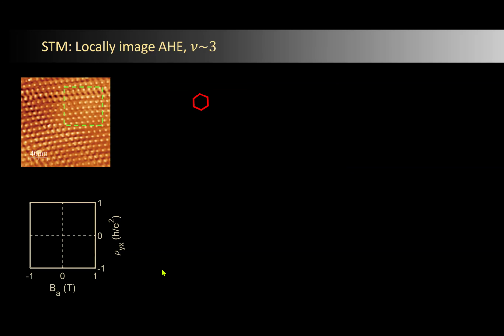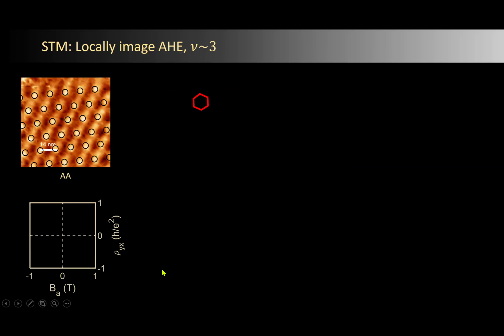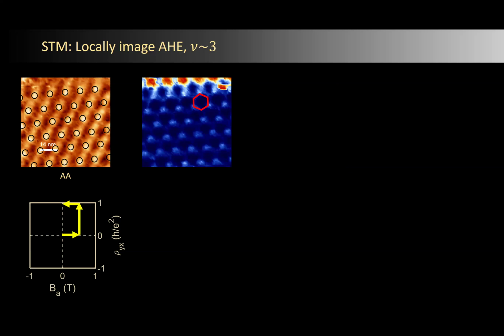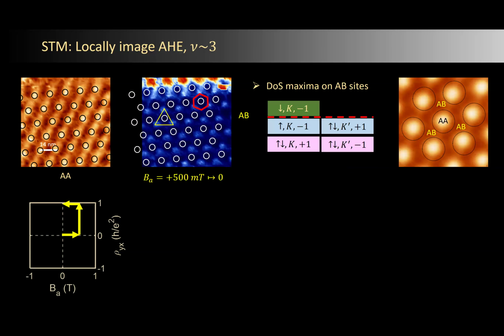So we're looking at this corner here, and I'm marking the AA regions. And now I'm applying a magnetic field. I'm going to a finite field here, and then I'm coming back. So I'm going to 500 millitesla, and then I'm coming back to 0. And I'm doing the density of state map. What I've done here, I mapped the AA region to the topography figure, and they're here. But I see the maximum of the density of state is shifted by a little bit. And it's sitting, actually, instead of being at the AA, it's shifted to the AB.